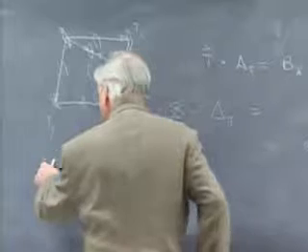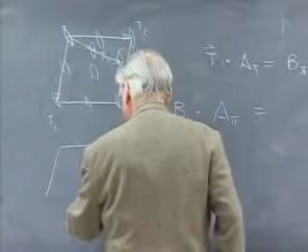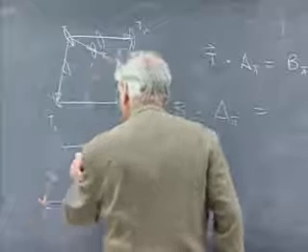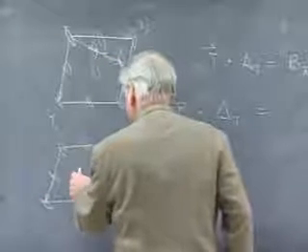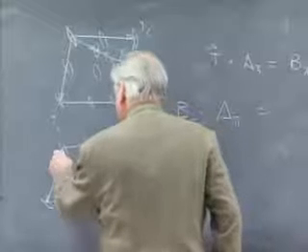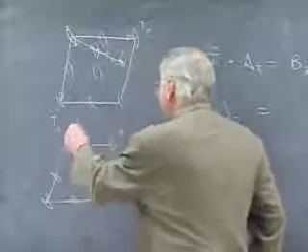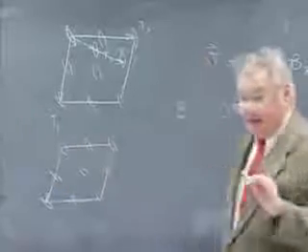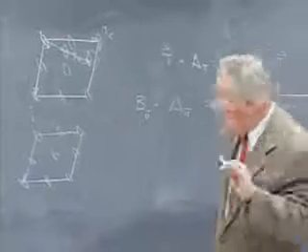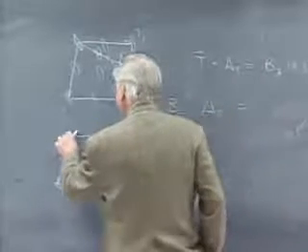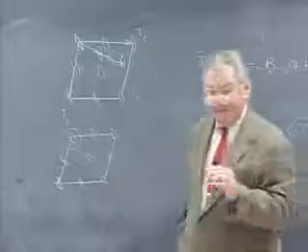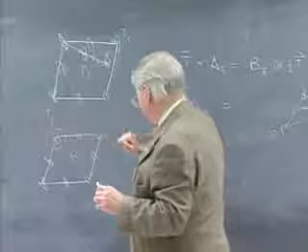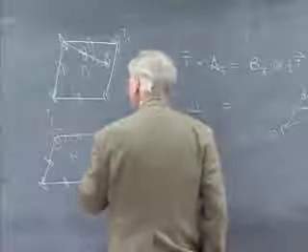So the conclusion then is that if we're going to safely pick a third translation T3 and combine it with a net that has twofold axes in it, in order to get a group, we are going to have to ensure that the twofold axes line up in every net in the stack. And there'd be several ways of doing that. We could pick T3 so that it goes straight up. Okay? And then the twofold axes are just all slid up parallel to themselves and they remain in coincidence.